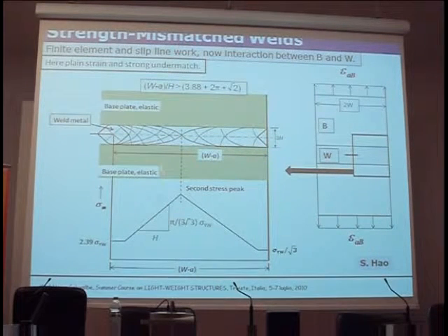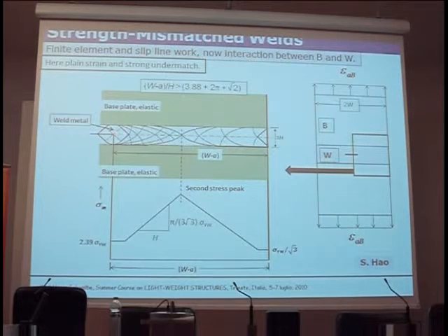And when you do the analysis for a crack in the middle here of the paper or the interface, there is not much difference. But the interesting point here is this analysis was done for this plane, okay, for the center plane, for the crack path plane. And so Hao did the same thing for the crack, still staying here, but for the situation here at the interface, and there's not very much of a difference. So this is really puzzling, and we found that very interesting.